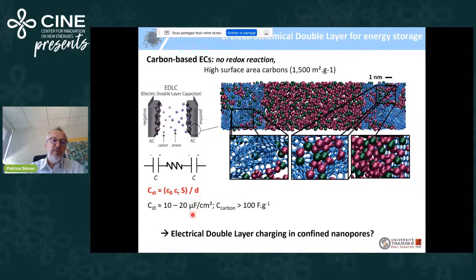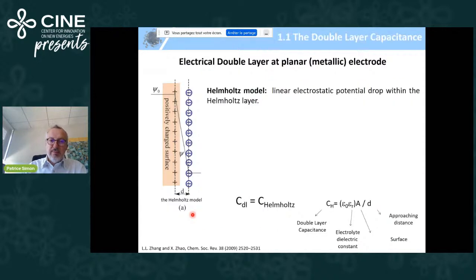And then at the end, you end up with 10 to 20 microfarad per square centimeter of double layer capacitance for conventional porous carbons. However, now the question is how this electrical double layer charging is achieved in confined nanopores. And before going in depth into the science, I'm going to give you some basic reminders about the electrical double layer at a planar 2D metallic electrode.